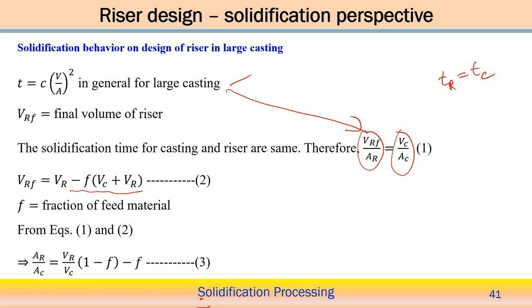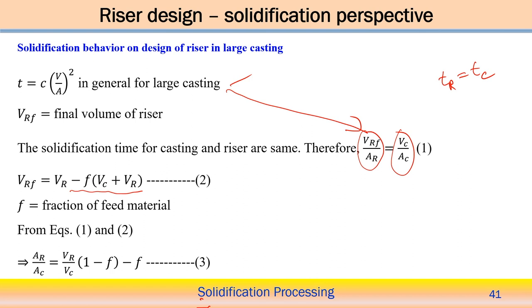So we count the fraction of the feed material, and based on that we can estimate the total shrinkage volume, because shrinkage will occur both in the cast volume as well as the riser volume. In both cases we get shrinkage, so we can take care of the shrinkage volume for VC plus VR, and F is the fraction of the feed material. Now if we consider equations 1 and 2, with simple manipulation we can get this expression: AR by AC equal to VR by VC times 1 minus F, minus F. This is equation 3, in terms of F, the fraction of the feed material.